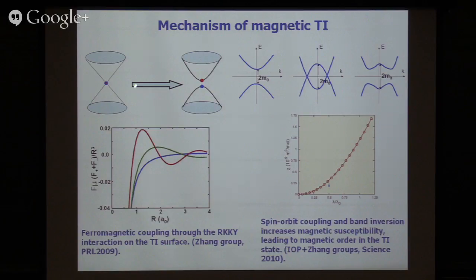But now the interesting thing is that when you put the magnetic moments on the surface and put the Fermi level exactly at the Dirac point, there's no k_F. So the magnetic interaction mediated by the surface Dirac electrons does not oscillate. Which sign does it have? We actually calculated it's always ferromagnetic. So the surface prefers to order ferromagnetically because the effective interaction doesn't oscillate. It's always ferromagnetic.